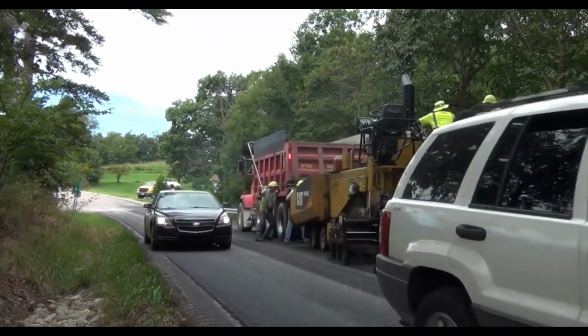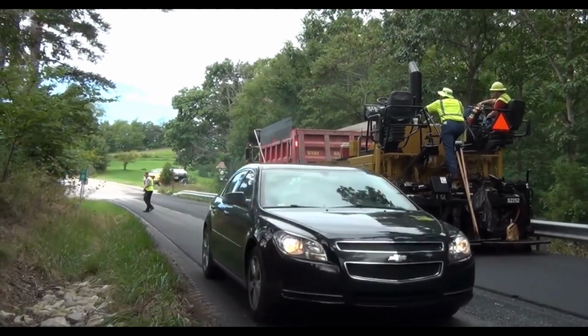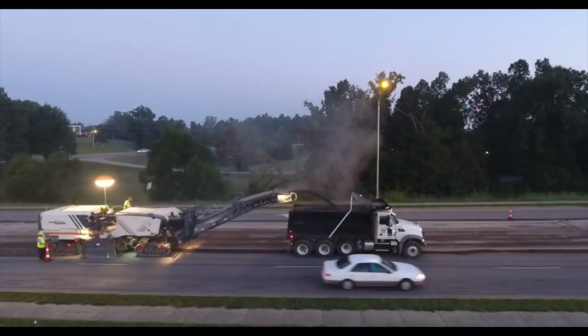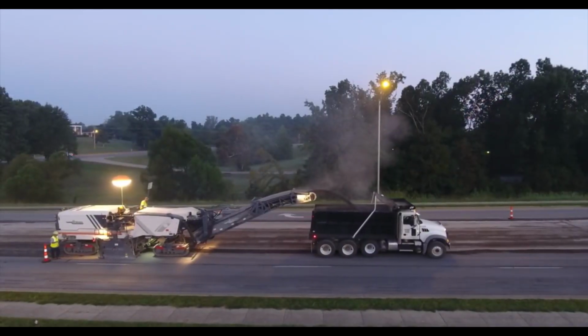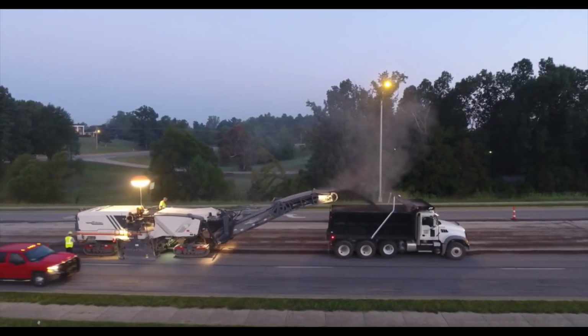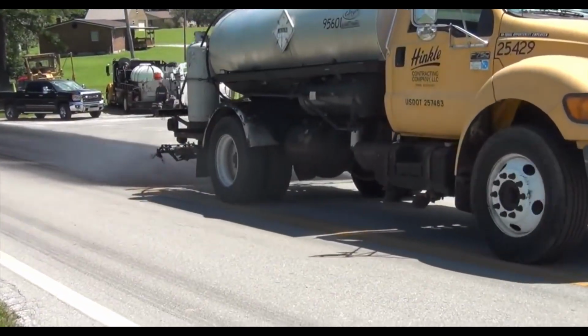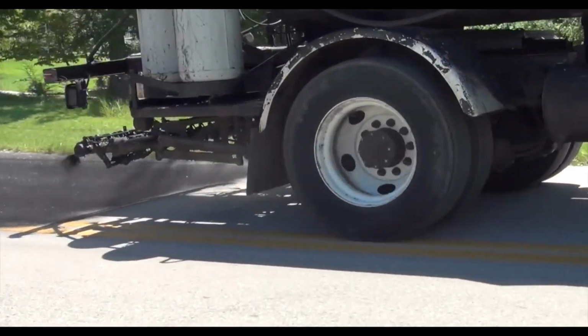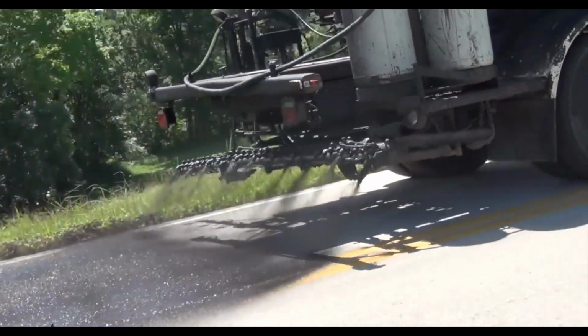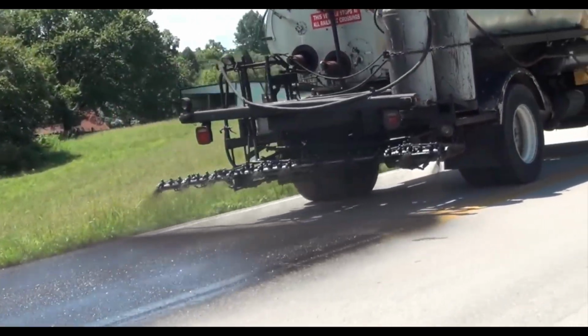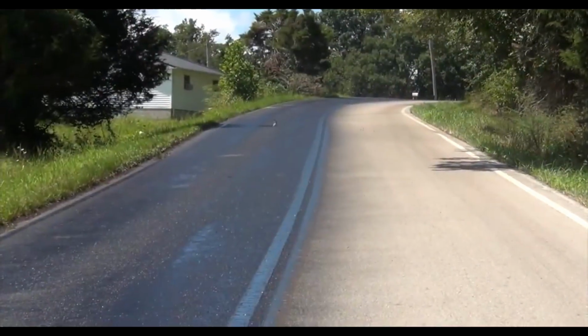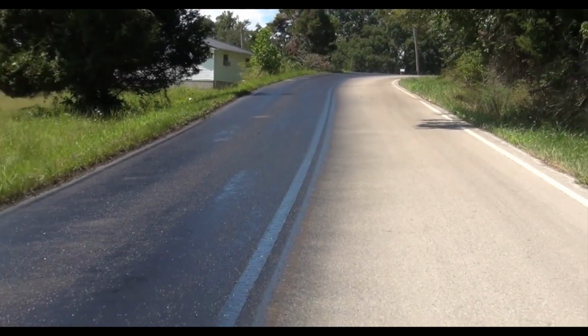Before paving begins, the underlying surface must be properly prepared. This may involve milling the old surface and sweeping away excess dust and debris. Applying a fresh tack coat layer helps create a tight bond between the new and existing pavements. With the surface ready for new asphalt, the paving train can mobilize.